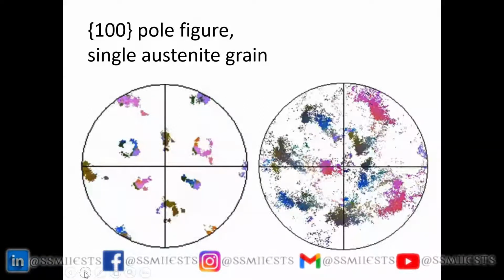On the right-hand side, it is deformed and then transformed into martensite. So what we've done is we've broken up the martensite into very small regions in what should be a single crystal of austenite, but there are severe orientation gradients inside each austenite grain, and therefore we have broken up the 24 variants that you normally get in a single austenite grain to thousands of variants, which are misoriented with respect to each other. Okay, so the next slide.